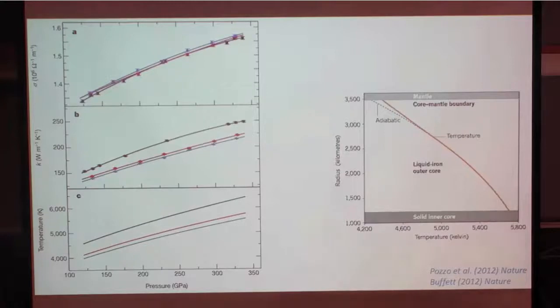In order for something to convect, the heat transported by convection has to be greater than the heat transported down the adiabat by conduction. Okay? And this conductivity is so high that it may actually shut off convection in parts of the outer core. What these guys estimate is that you might have a stably stratified layer at the top of the outer core, and that obviously changes the temperature distribution in the core.